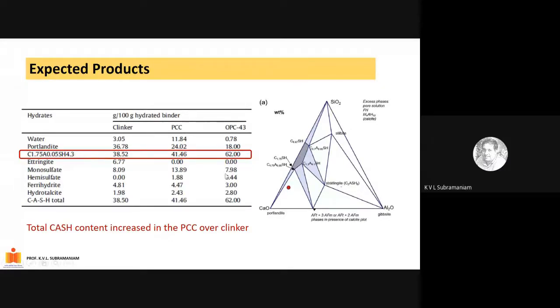And we compared it with the ordinary Portland cement, which is commercially available, grade 43. We found that it is lower than what you get from OPC 43, but we were able to produce a higher amount of CSH in the system compared to what I would get from pure clinker. So therefore, the composite cement actually would give us a higher strength when compared to pure cement.